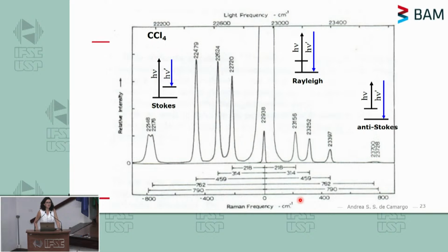But of course, what we are interested in measuring when we want to characterize the vibrational structure of the glass are the Stokes lines here, because they are detectable. This difference in frequency from the Rayleigh to the Stokes line will give me the vibrational energies of the glass, as you can see here, right? And then we often talk about phonon energy, and we say the maximum phonon energy, the maximum vibrational energy of the glass is, I don't know, 1,000 cm^-1.